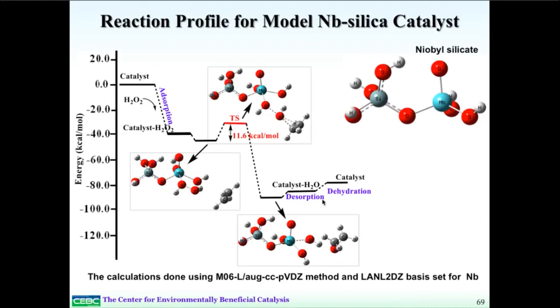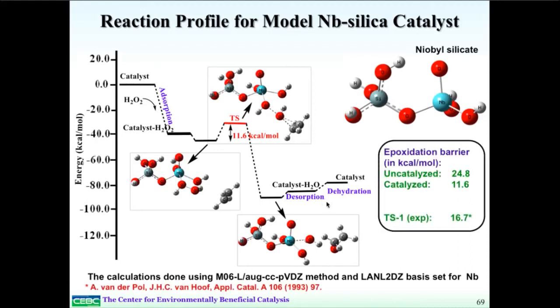If you look at this, the uncatalyzed reaction, this transition state is about 25 kilocalories per mole. With the catalyst, it goes down to about 11.6 according to the calculations. And this is favorable relative to a TS1 catalyst, which is about 16.7. So here we can map out this pathway pretty rigorously.